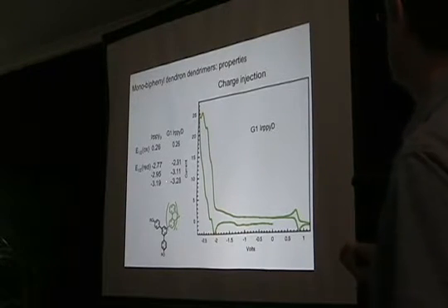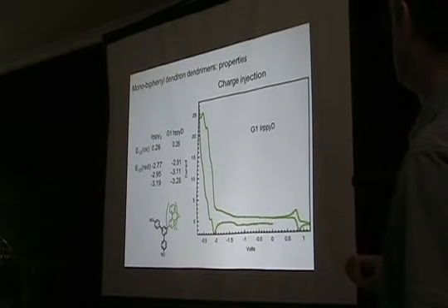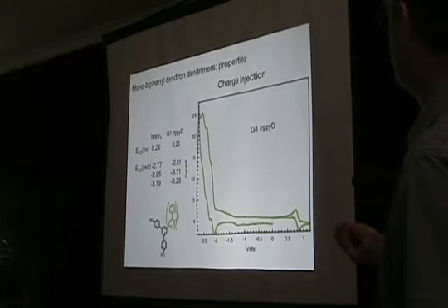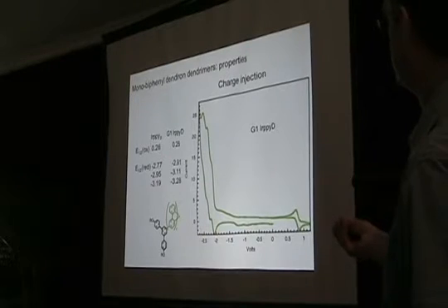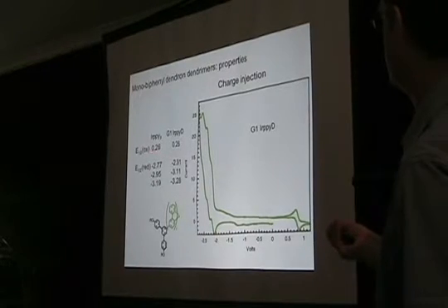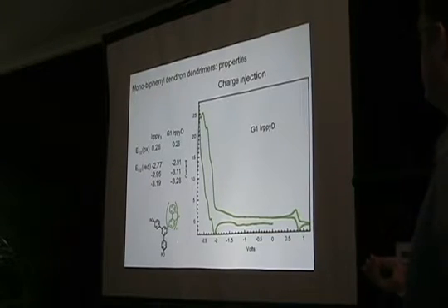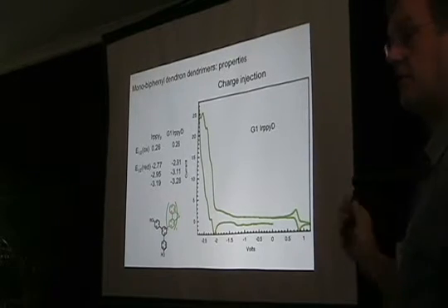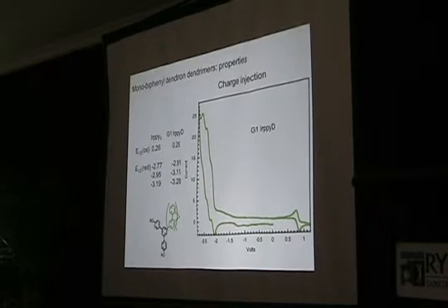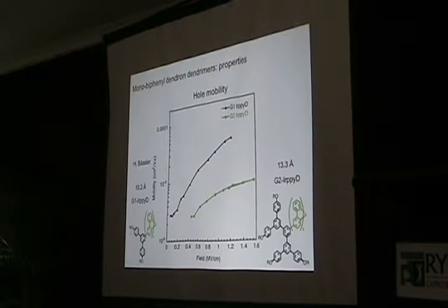And the simplest way of doing that is to do a comparison with just a simple complex. And so you can see here the electrochemical results for the complex. And you can see the oxidation occurs at 0.26 volts, similarly for the dendrimer. And on the reductions, we're basically in the same position. So what that's saying is that for this dendrimer here, the charge gets injected into the core and not the dendrons. So the dendrons, if you like, are electrically insulating and act as rigid structures.